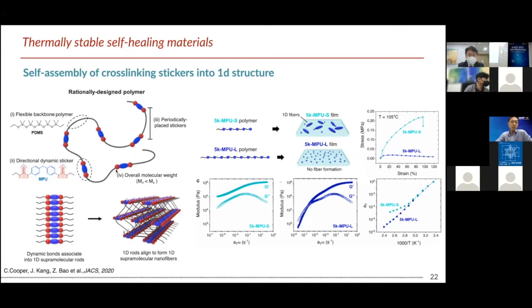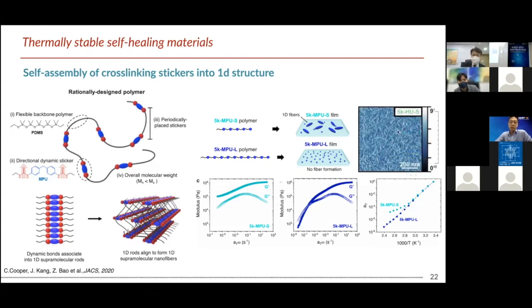Even with the same molecular design, by controlling the overall length of the polymer, we found that we can promote a fiber structure in the polymer film with the dynamic bond. Then we found that even at 100 degrees C, a relatively high temperature, this nanostructure can still be maintained and shows really nice mechanical properties. This is the fiber structure seen by AFM. As you can see, these dynamic cross-linkers start to form a very nice 1D structure and dramatically change their mechanical behaviors. Also recently we developed a very nice actuator based on this supramolecular polymerization method.